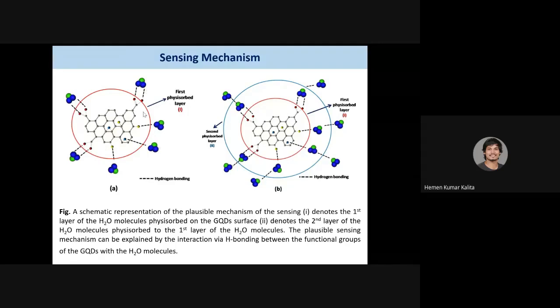These water molecules come and interact with these oxygen functional groups, and they will physically absorb onto the oxygen functional groups by loosely bound hydrogen bonding. The first layer which comes in contact with the graphene oxide is known as the first physisorb layer. And as more water layers come, the second layer will interact with the first layer, the third layer will interact with the second layer, and so on. So there will be a chain of physisorb layers. In this diagram we have shown how the first and the second physisorb layers are attached.